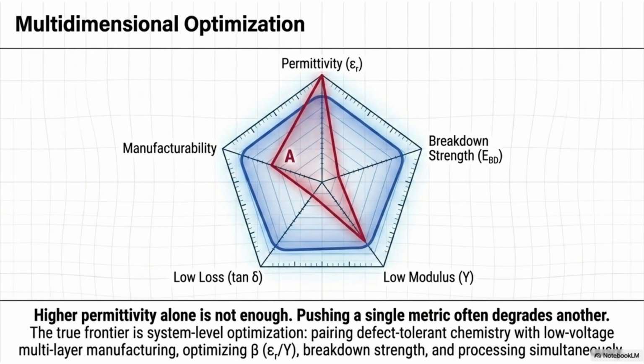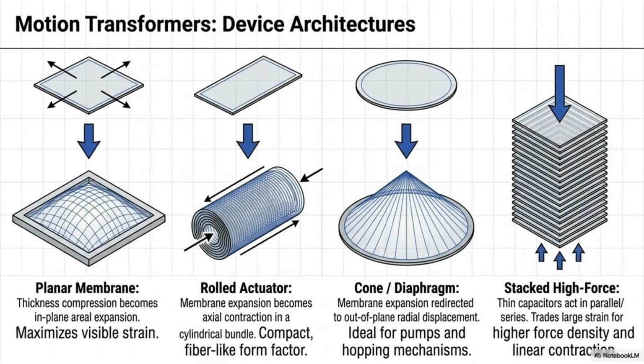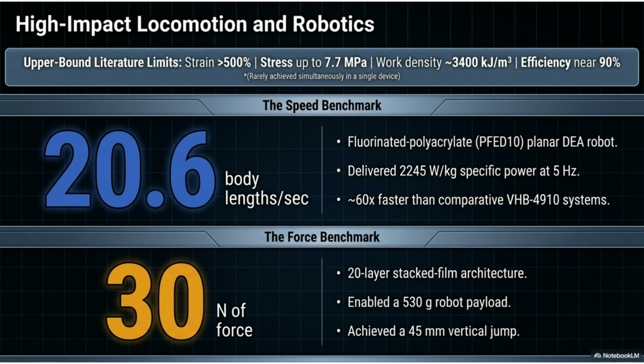Optimization of dielectric elastomer actuators requires a multi-dimensional approach. Focusing only on a single metric, such as higher permittivity, can degrade other important characteristics like breakdown strength and low modulus. System-level optimization is the true frontier. DEA architectures act as motion transformers. Examples include planar membranes for in-plane expansion, rolled actuators for axial contraction, cone/diaphragms for radial displacement, and stacked high-force structures for linear contraction. DEAs enable high-impact locomotion and robotics.